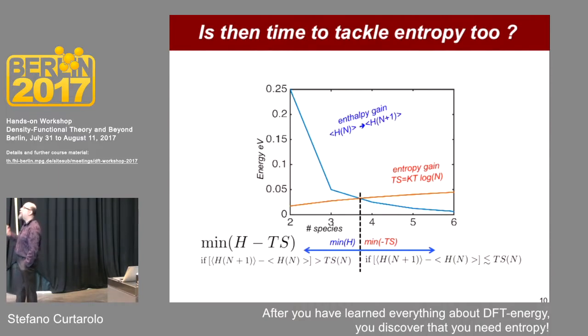What does it mean? It means that when Gibbs tells you that to find the stable phase, you need to minimize the Gibbs free energy, which is the minimum of H minus TS. If you are below this threshold, you don't care about entropy. You only minimize H. If you are above this threshold, you don't care about enthalpy, and you only minimize minus TS. Min of minus TS is max of S, right? So below this threshold, enthalpy plays a role. Above this threshold, entropy plays a role.